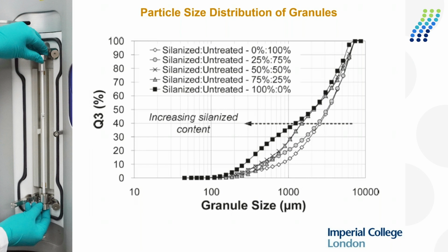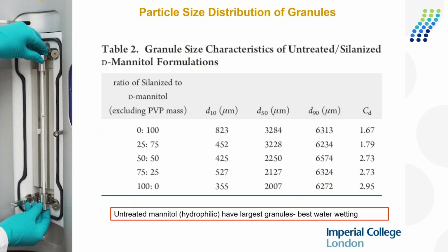So in other words, if I've got very good wetting between my binder agent and my particles, if all other things are the same, I will get larger particles, larger granules, than I will get with a more hydrophobic material. So firstly, hydrophilicity affects the granule size that we end up fabricating. And the sizes are given in slightly more detail here. You can see that we've got 2 millimeters to 3.3 millimeters, so basically about 60% larger for the hydrophilic materials.